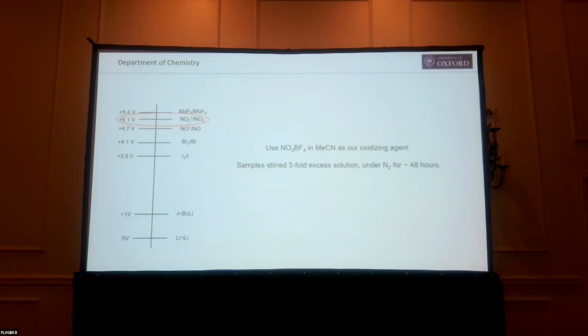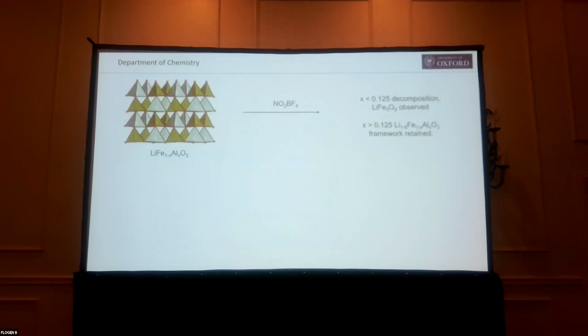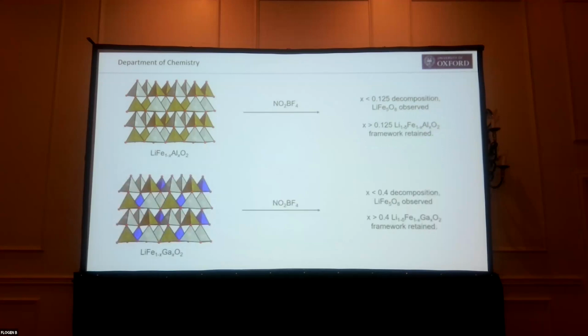So what about oxidation? What we're going to use for our oxidation chemistry is the nitronium ion. We're going to use nitronium BF4 in acetonitrile as our oxidizing agent, and we're going to stir up our reagents. And now we see actually the aluminium helps. Once we get more than an eighth substitution of aluminium for iron, we can actually stabilize the vertex-sharing framework and retain the material. And in the gallium case, we need 40% substitution to stop this collapse forming, but again, we can get retention.